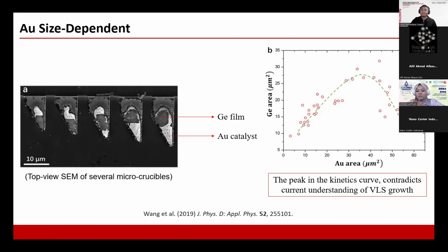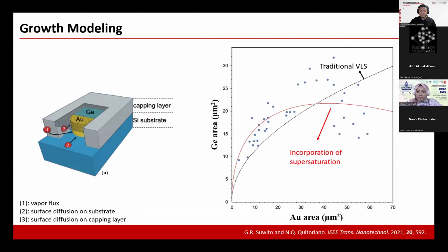This kind of behavior, if you are in the VLS nanowire growth community, is actually very, very strange because the traditional understanding of the VLS growth doesn't predict this behavior at all. So to reconcile this, we tried to develop a growth model, assuming that the germanium film is in a rectangular shape, and then the gold catalyst is in a half-cylindrical shape like that. And there are three contributions to the growth. The first is from the net vapor flux, labeled (1), and the second is from the substrate diffusion, labeled (2), and the third contribution is from the capping layer diffusion, labeled (3) in here. This model is shown in the black curve in the germanium size versus gold size.